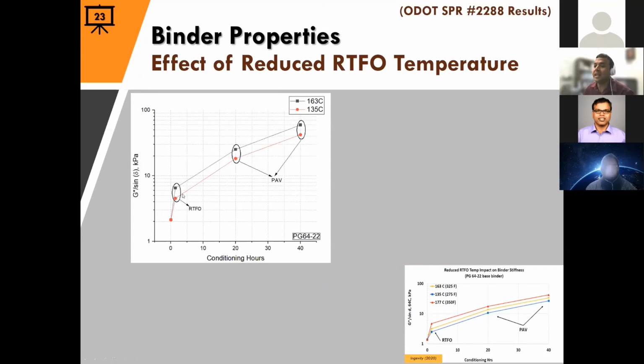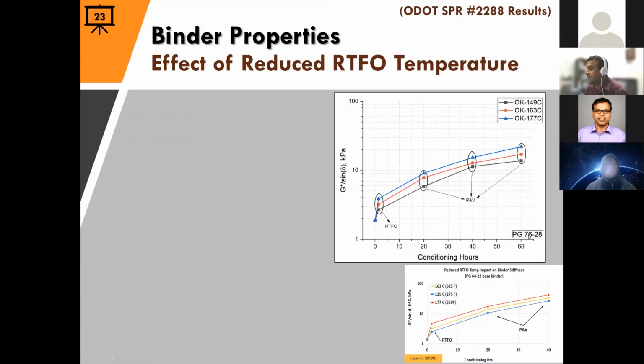As you can see, in the initial aging there is a big gap, and that gap stays parallel as you increase PAV aging. For this binder, we went into 2 cycles of PAV. For the next binder, which is a 76-28, we went into 3 cycles of PAV at different RTFO temperatures. And we are seeing that the lines are pretty much parallel during PAV. Of course, there is a little bit of deviation here, but the biggest difference happens at the RTFO temperature. In other words, the stiffening of the binder is happening mostly during the short-term aging, during production. If we reduce temperature, we will probably benefit significantly, right?